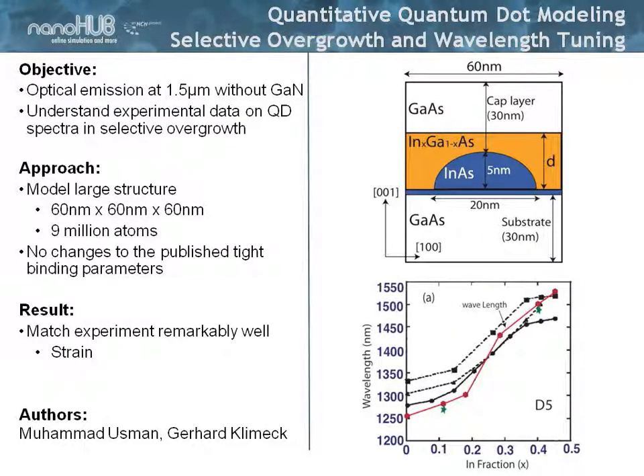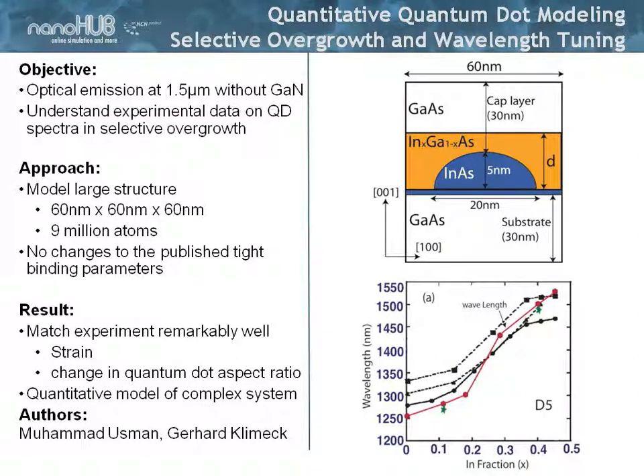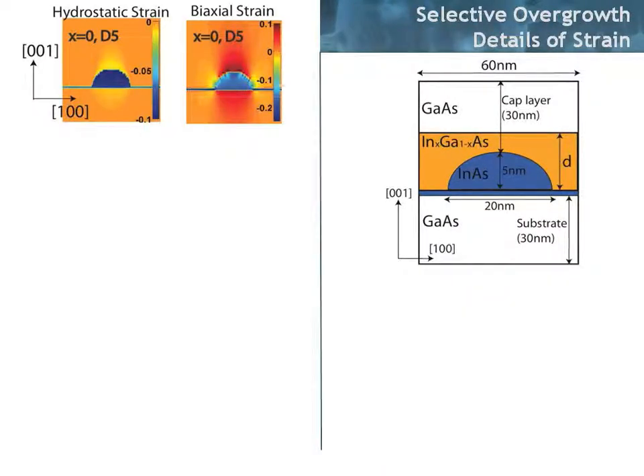Obviously strain is important — that's clear from the previous presentations. But there's something interesting: the quantum dot actually changes shape as you overgrow it with a strain layer, which is very unusual. With those two major components we can explain more intuitively why we're overlapping theory and experiment. If you start out with a quantum dot system that is not overgrown with a capping layer and you plot the hydrostatic strain, you see that the hydrostatic strain is roughly confined to the inside of the dot — it seems like hydrostatically this quantum dot feels like it's being squeezed from the outside.